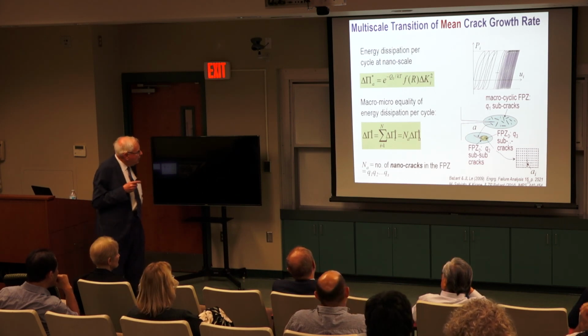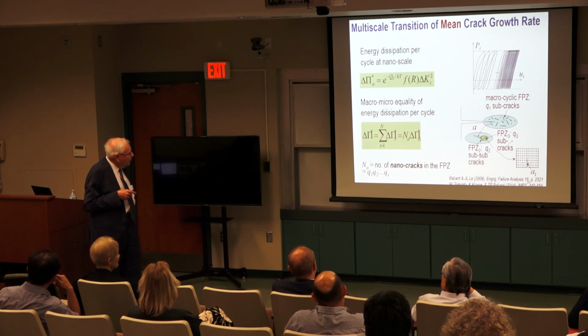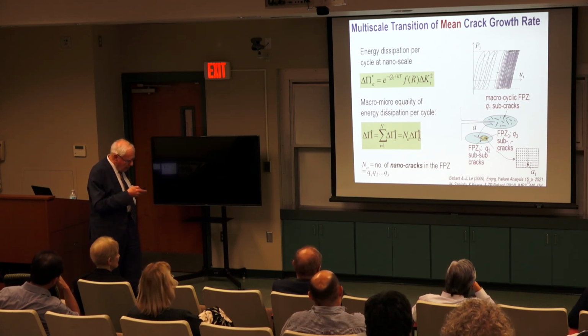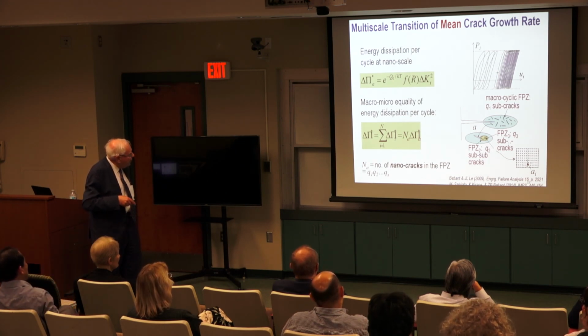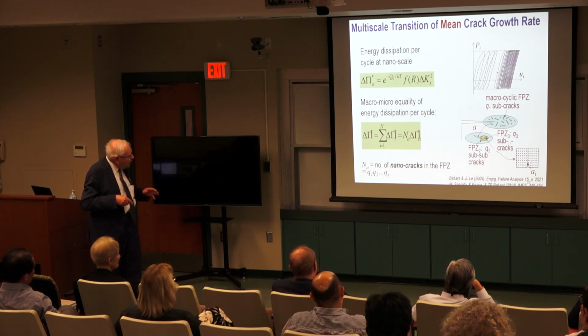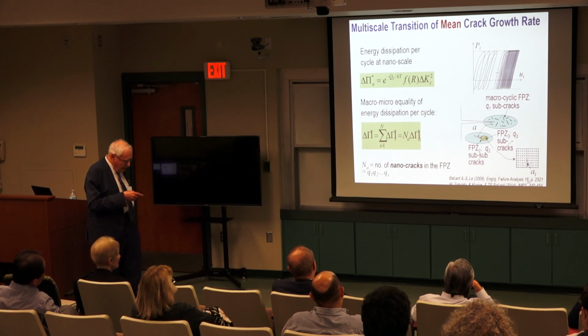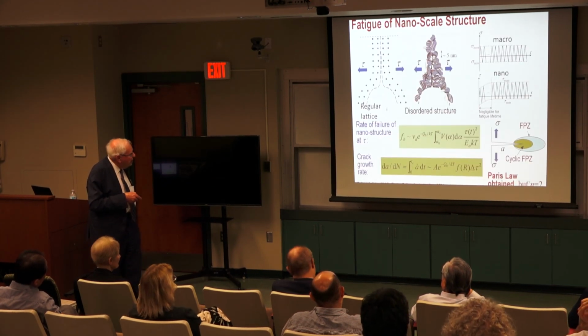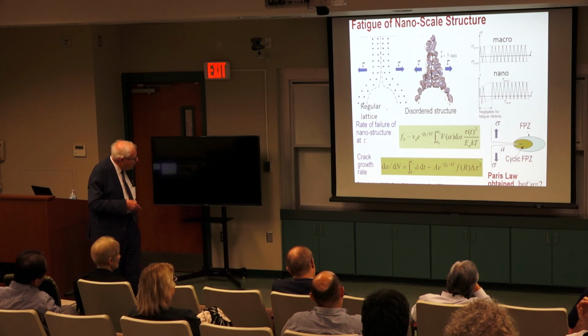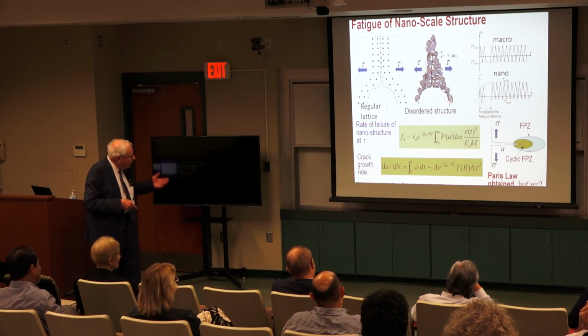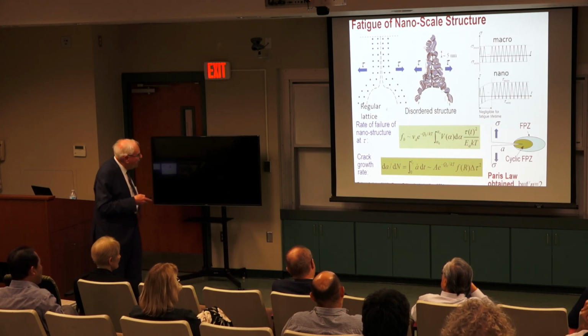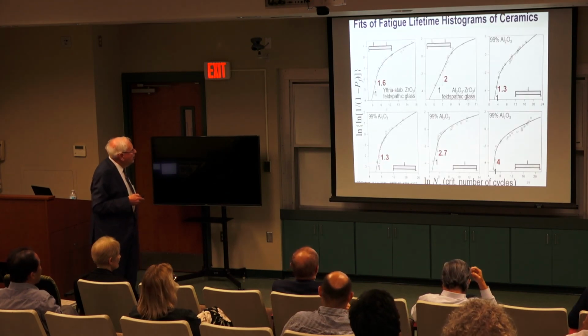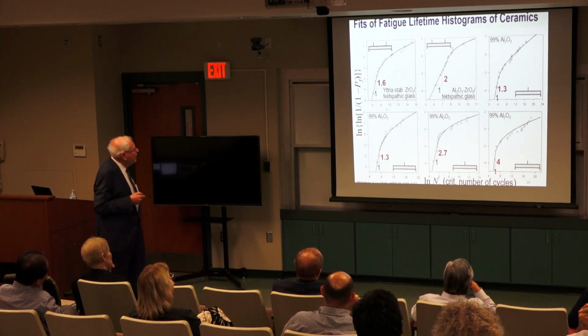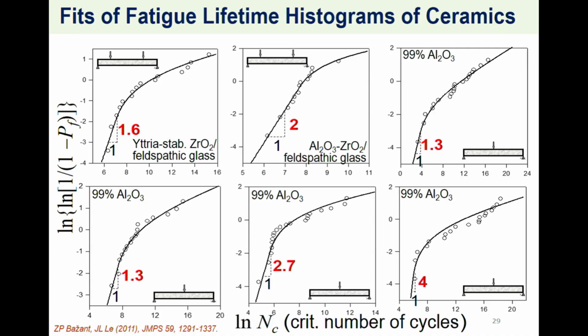It's subcritical. So it's not a question of failure, it's a question of dissipating the same amount of energy per unit advance of the crack or per unit cycle on the macro and micro scale. If you impose this condition, then energy dissipated on macro and micro, you conclude again that the tail is growing, and from this distribution with a square exponent, you get to higher values for concrete, about 10. Same kind of behavior. And then you can calculate lifetime. So these are fatigue lifetime histograms for ceramics of various materials. You see for lifetime the same behavior.